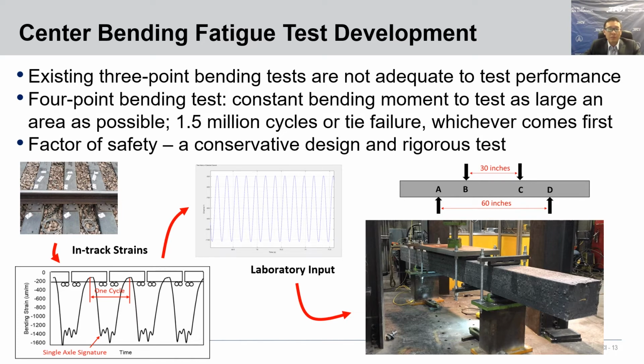However, a longer inner span reduces the length of sections AB and CD, therefore increasing the shear forces in those two areas, and could result in shear failure instead of tie bending failure. We performed trial tests using different spans, and during these trial tests, a 30-inch inner span was able to generate the tie center cracks without shear failure.